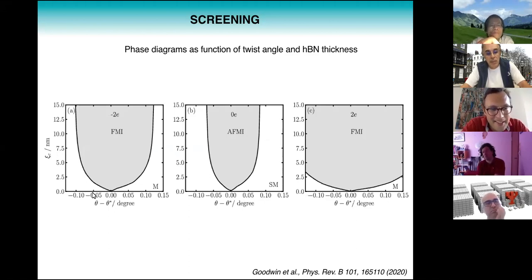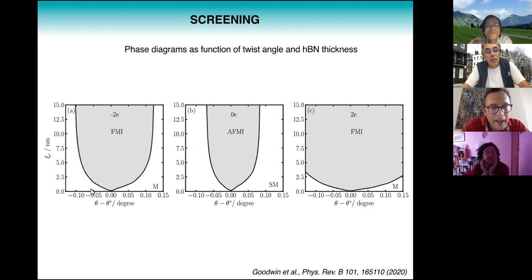Now, how should you interpret these graphs? So, okay, let's say we're at -2 electron doping, and we have a sample that is sort of -0.05 away from the magic angle. So we're sort of going up and down here. And what this tells you is basically, as you start from a very thick boron nitride layer, you have a broken symmetry phase. And as you go down, to a very thin boron nitride layer, something like 2.5 nanometers, your system goes from the broken symmetry state back to the metallic normal state.